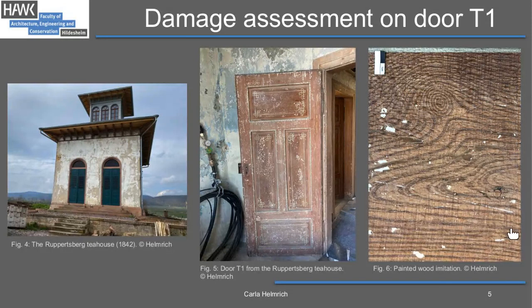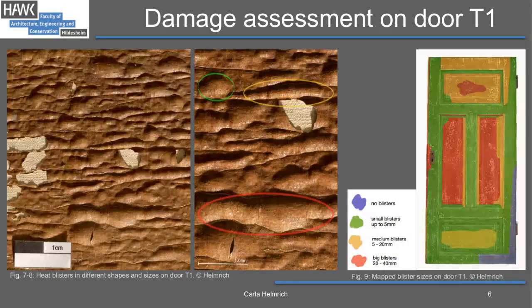The heat blisters were found on almost the entire surface of door T1 in a wide variety of shapes and sizes, as you can see in these two photos. The separation of layers occurred between the primer layers. The inner space of the blisters was hollow. Some blisters showed stomata or gaps, as you can see here in the surface.